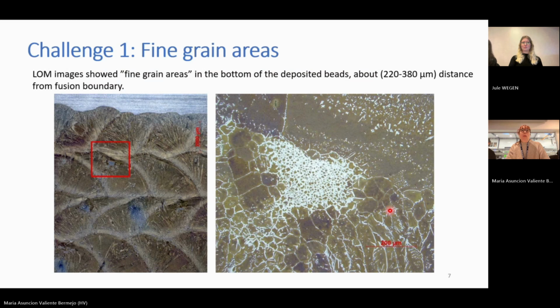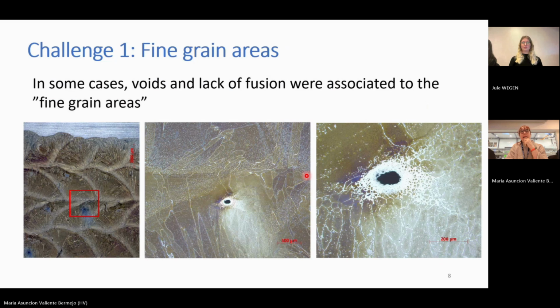So the first challenge was these fine grain areas. When we were depositing in the very beginning, we found these very small grain areas close to the bottom of the deposited bead. So they were placed at the bottom. We said, what is that? That was squeezing our minds. In some cases, these fine grain areas were together with voids or pores, lack of fusion. So it was not only the presence of these fine grain areas, it was also that sometimes they were associated with other types of imperfections or defects.